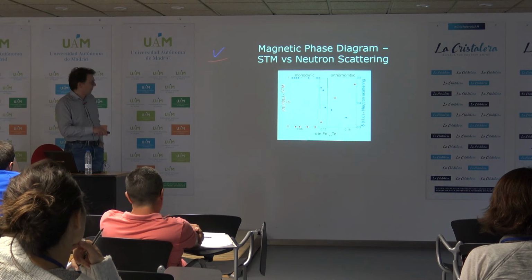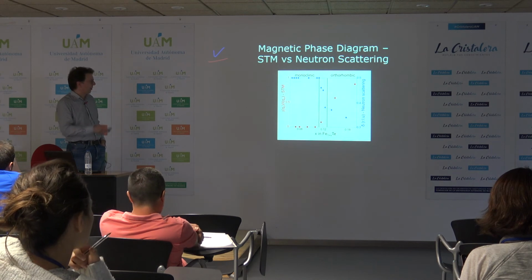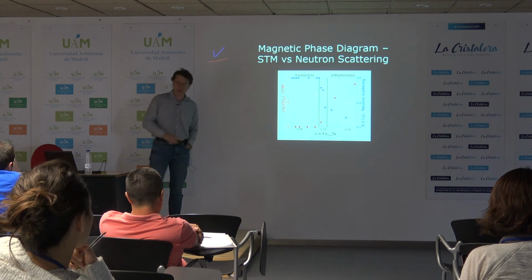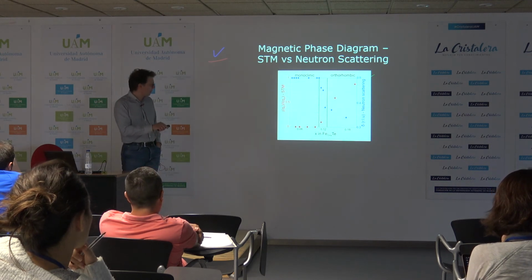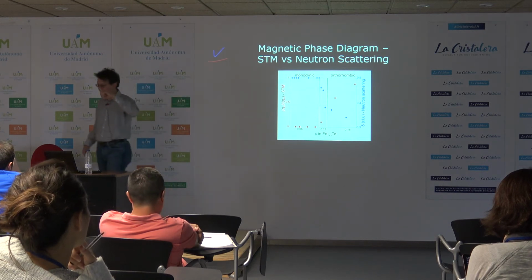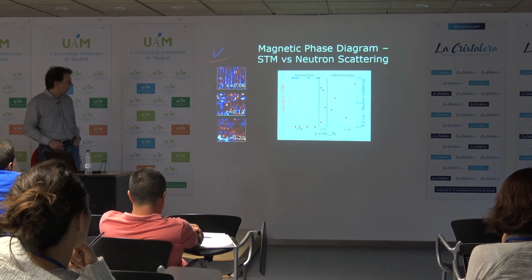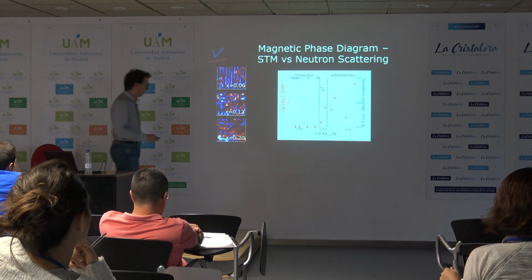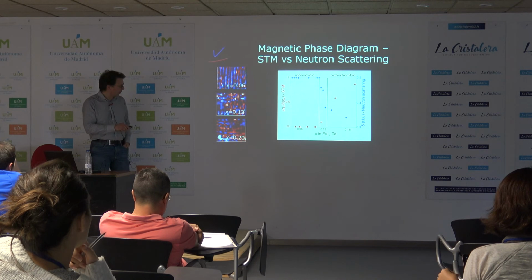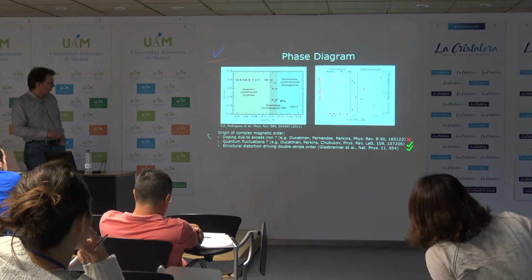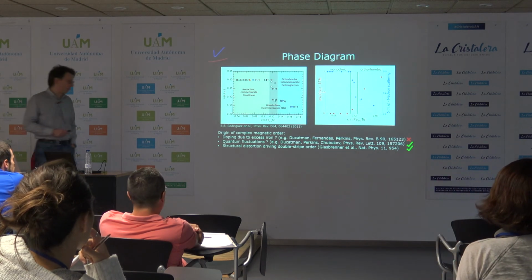So that's completely consistent. And then as we come to high excess iron concentration and the material undergoes a phase transition to orthorhombic structure, the Neutron scattering shows this incommensurability, and we start to see this double Q ordering in the orthorhombic phase, which is where the 2 lattice constants become more similar to each other, and you start to get this formation of a plaid magnetic order, which is well shown by the fact that you see intensity in both directions. Okay, and if we compare this now to the theoretical models which have been proposed for the magnetic order,